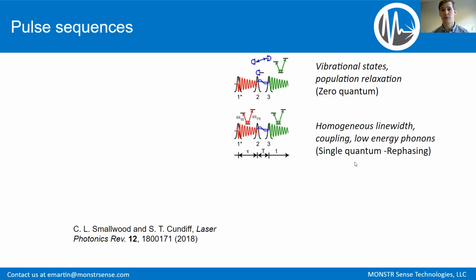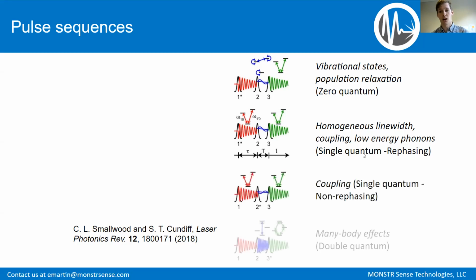What's great though, and the reason why we have all these pulses, is that there are other things that you can do. You can also spectrally resolve the pump. And so if you spectrally resolve the absorption and spectrally resolve the emission, as you would in conventional 2D spectroscopy, then you can get all kinds of additional information, right? You're now correlating the absorption energies with the emission energies, which lets you pull out those homogeneous properties. And there are other sequences as well for looking at other types of coupling. There's a sequence that exclusively pulls out many-body effects.